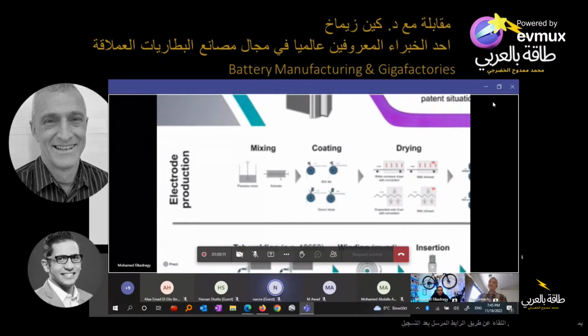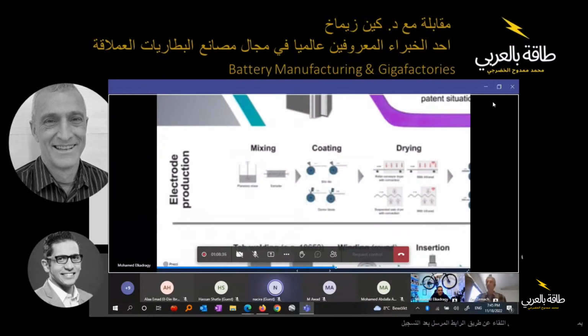The other thing is that if you're making a high-end NMC battery, lithiated nickel manganese cobalt is very reactive with water. So you do this in a dry room. So you can't use water for that reason either. So they usually use NMP, which stands for N-methylpyrrolidone. It's a little unfortunate that NMP sounds like NMC, which is nickel manganese cobalt, but NMP is a solvent. It is like diesel fuel, not technically flammable at room temperature. It's a great processing solvent.